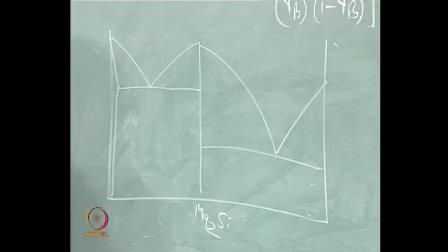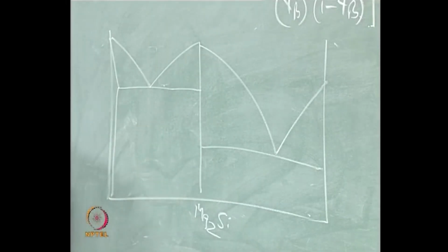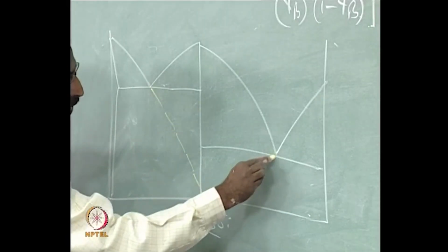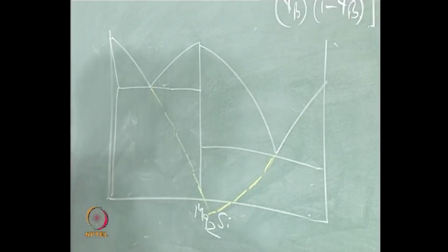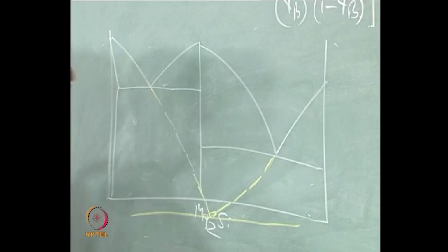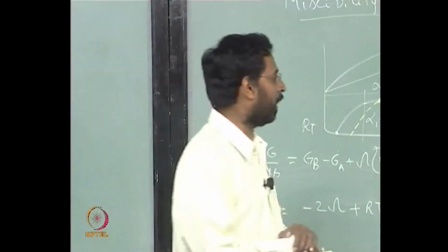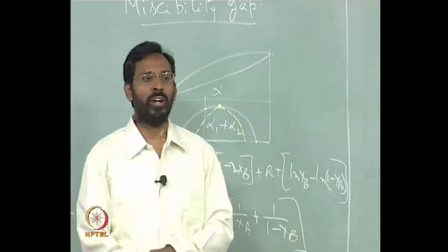Then what should come out? The liquid would remain as liquid, and it would remain as liquid if you extrapolate these liquidus curves to a particular point where you have another eutectic, which is what we call a metastable eutectic. So, in a phase diagram, if there is a normal eutectic like iron boron, I can say yes, that is a composition where you can get a glass.